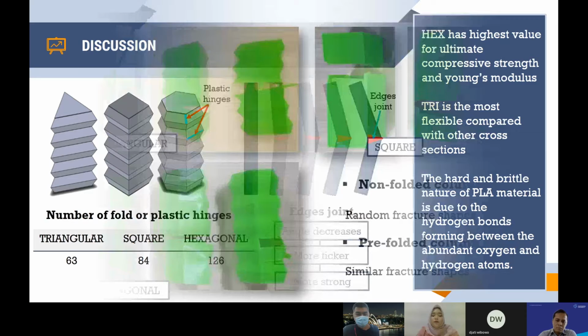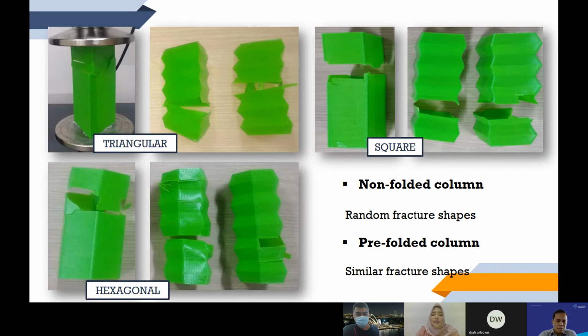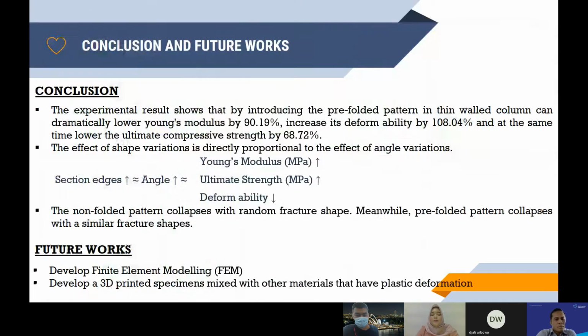From this, the non-folded and pre-folded thin-walled columns show different failure modes. The non-folded pattern collapses with random fracture shapes, meanwhile the pre-folded pattern collapses with similar fracture shapes. This happened because of the geometric imperfection, or folding pattern, that leads the thin-walled column to deform by following the folding pattern. In conclusion, this experimental result shows that introducing the pre-folded pattern in a thin-walled column can dramatically lower Young's modulus by 90.19%, increase its deformability by 108.04%, and at the same time lower the ultimate compressive strength by 68.72%.